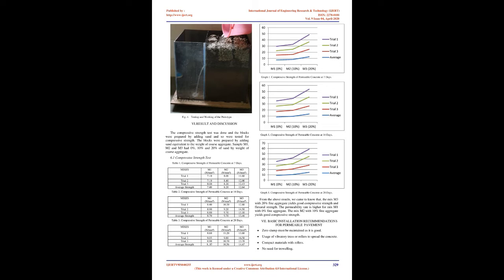4.6 Preparation of specimens for testing. The specimens were taken out from the curing tank on the testing day to prepare them for testing. Surface water and grit were wiped off and the specimens were allowed to dry for about 1 hour. The specimens were marked according to their respective mixes.